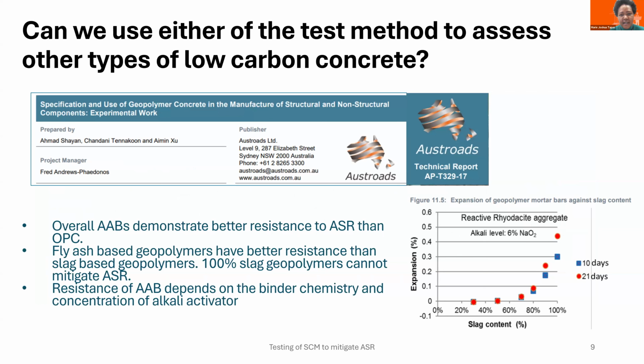Alkali-activated binders, I think more studies are still required, particularly for other durability deterioration mechanisms and other durability concerns. But this work by Austroads is probably the most comprehensive I've seen in terms of alkali silica reactions. If you go through this publication, they've investigated several chemistries of alkali-activated binder systems. And overall, they still demonstrate better resistance to ASR than typical cement. Fly ash-based geopolymers have better resistance than slag.